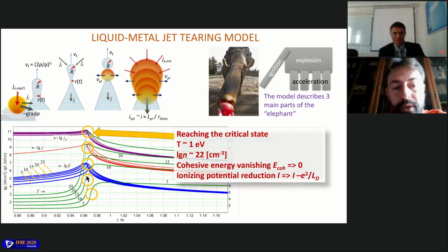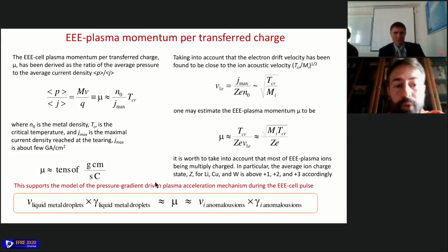And there is tearing of the jet, increasing of current density, transition to the critical state, and we can propose some simple model. There is an example of temporal evolution for critical temperature for various materials. And we catch three main parts: ignition, explosion, and expansion of plasma after the explosion. So there are three main parts of the problem. What can we derive from this model? We can derive the mass of ions related to the current density, the number of electrons. So how much plasma should be produced for the current that we want to transfer.